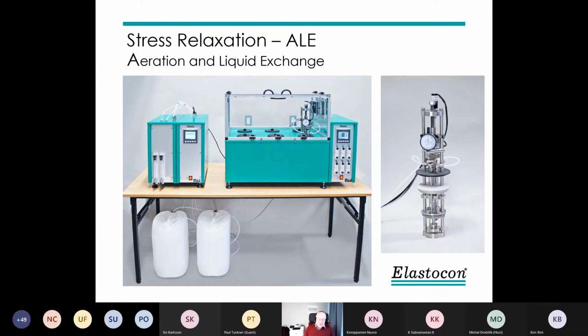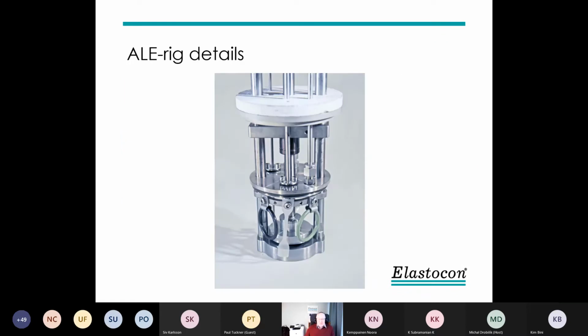And of course, in a fuel which is used in the fuel tank in a car or a truck, you have air present. So you need air during the aging. Two years later, we made another project with the same participants, but this time we looked at motor oil. In motor oil, you also have air present. So also there it's interesting to introduce air in the system. We also made a little holder here so you can put in samples, could be O-rings or small tensile bars. So you can do these other types of tests after you finish the relaxation test, but they have been done in the same environment. This can be also adopted on all normal relaxation rigs.